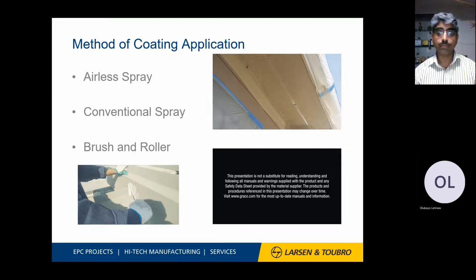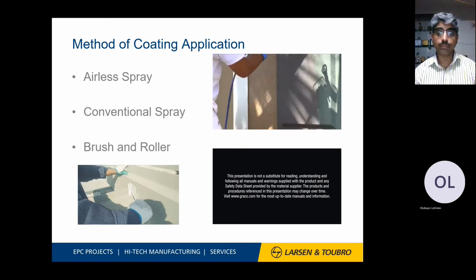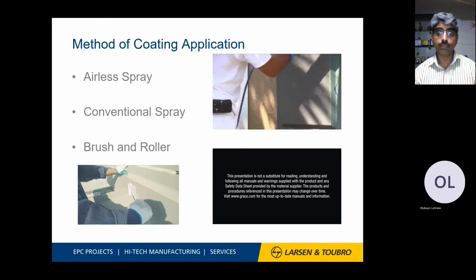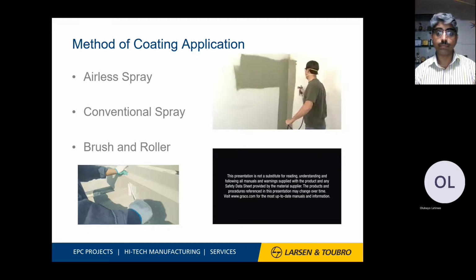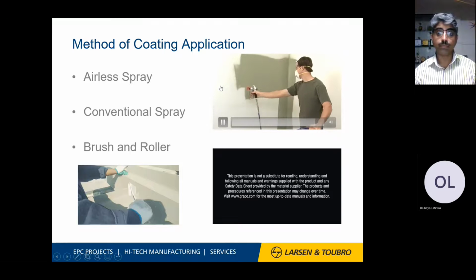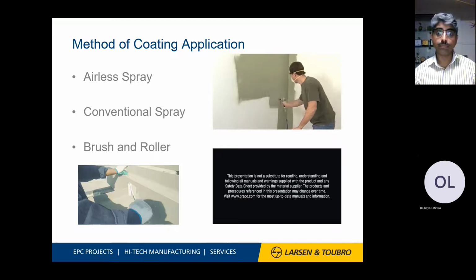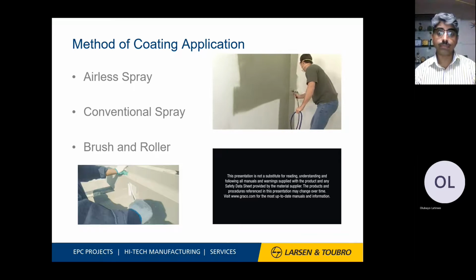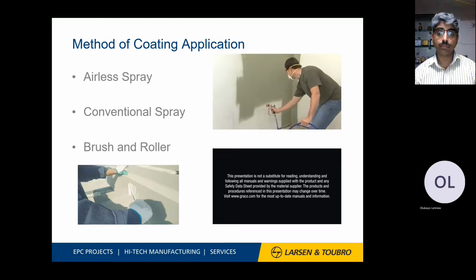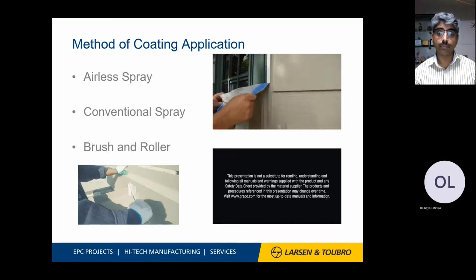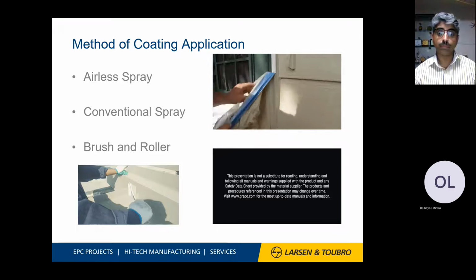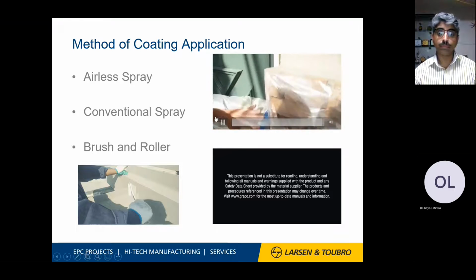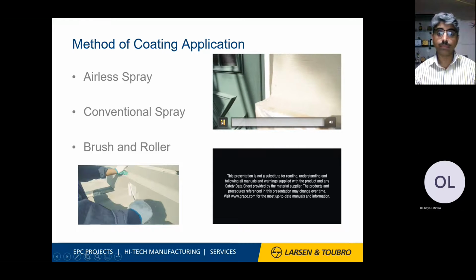With a little practice, this easy-to-use sprayer will have you spraying like a pro in no time. Remember, point the gun straight at the wall without tilting up or down or angling left or right. Start moving the gun before and after you trigger. Move at a consistent speed, and when spraying, overlap the prior spray pass by 50%. Allow enough time for paint to dry before removing tape from your trim. This will result in crisp, clean lines.